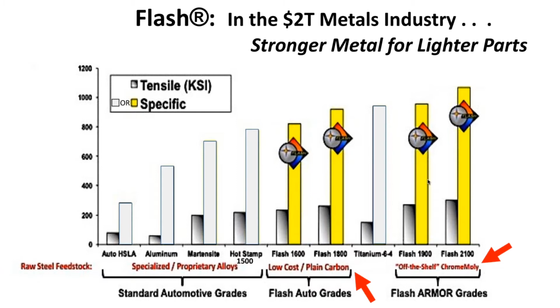Comparing to martensite or hot stamp 1500, you move a little bit over and now you've got the standard automotive grades. If you consider flash 1600 or 1800 made from low cost plain carbon steels, moving over one more step, you come to titanium 6-4 STA bar. And then you've got flash 1900 and flash 2100 KSI strength, or our 500 Brinell and 600 Brinell armor made from simple off-the-shelf chrome moly steel.